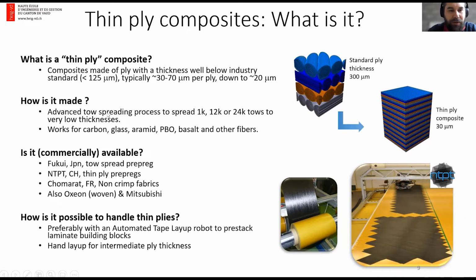And it's made by advanced tow spreading process, where the typically carbon fiber tows are spread very thinly to a few fiber diameter thickness, and then impregnated or stabilized to make non-crimp fabric, for example. These materials are commercially available, not necessarily widespread, but commercially available.